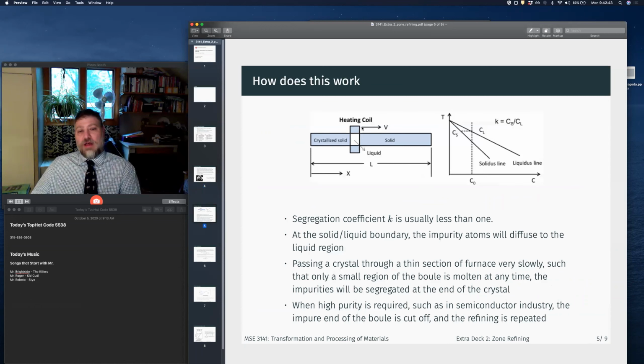Well, essentially it uses the theory that we just talked about. If I have an alloy of composition C_0 here, and I melt it and then re-solidify it, my solid is going to have less solute in it than the liquid. I'm going to reject solute from the solid as it freezes into the liquid. So the segregation coefficient, or partition coefficient, k, is typically going to be less than one. At the solid-liquid boundary, the impurity atoms are going to diffuse into the liquid.